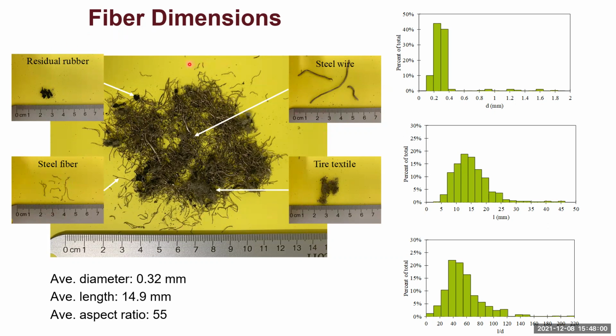Then we did a fiber dimension measurements. So the average diameter of the steel fiber in the samples we collected is 0.32 millimeter, and the length is about 14.9 millimeter. And the aspect ratio is 55, which is very normal for steel fiber that is being used in concrete.